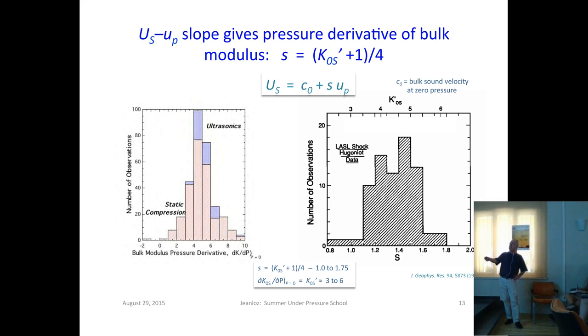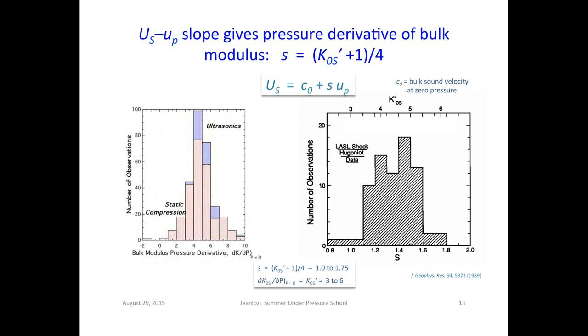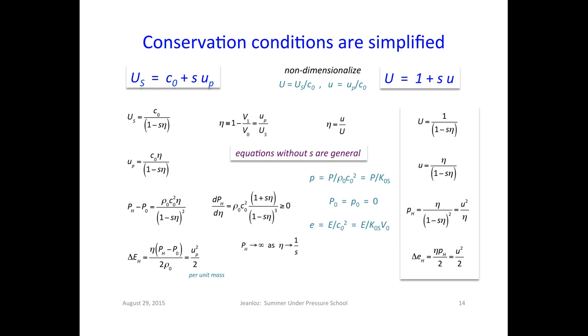This relationship is derived exactly by going through an equation-of-state analysis. We're getting real thermodynamic and elasticity data out of the shock waves. At very low stresses and very low impact velocities, a shock wave is just like an elastic wave. For this simple equation of state, we can rewrite our conservation equations in simplified form for the linear shock velocity–particle velocity relationship. The pressure goes as the strain — volume strain divided by another factor — we can get the derivative of the equation of state, and we can get the energy change as well.